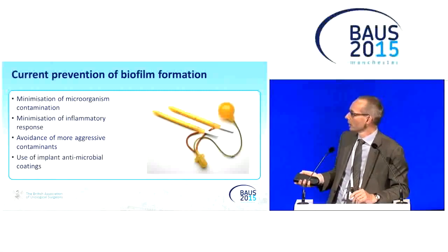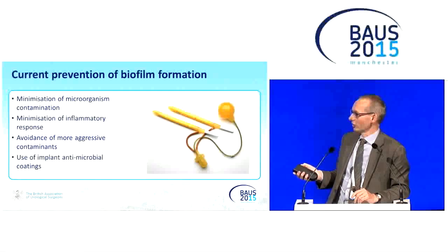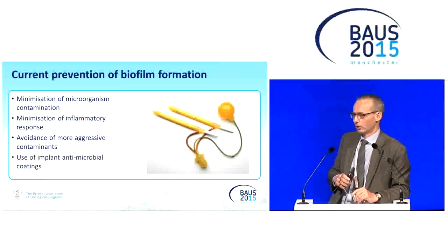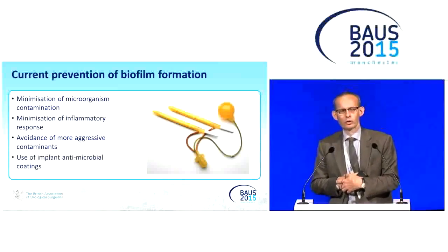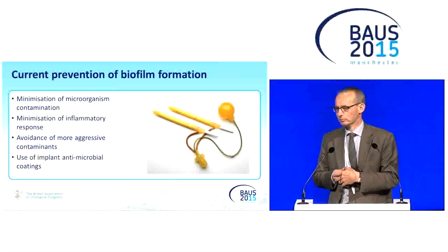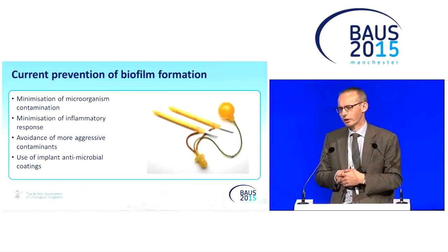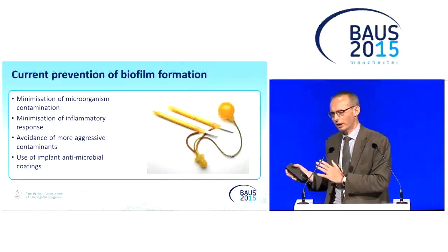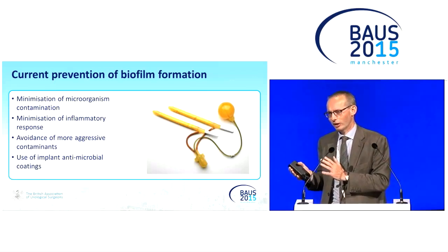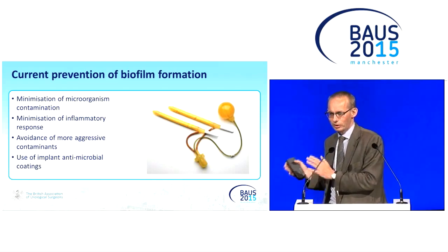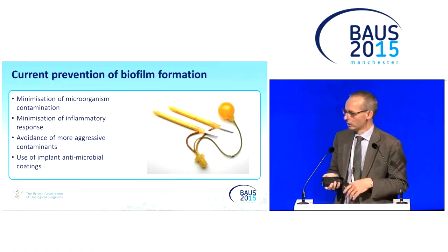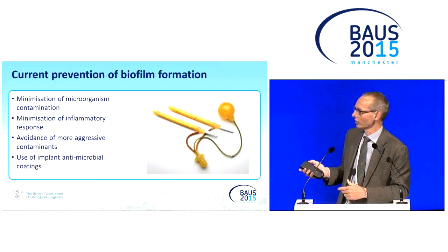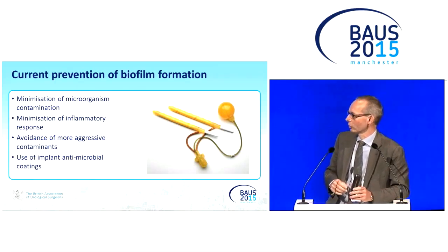And then one of the latest innovations on these implants, particularly the AMS ones, has been the coating of the implants with a mixture of rifampicin and minocycline. According to the reports from AMS, and a lot of this does come from Steve Wilson's work, that tends to minimize the slow chronic sinus infection type formation that eventually leads to removal. So it tends to reduce that, but it doesn't seem to reduce the more aggressive infections that mean instant removal. So it has changed things for the better, and it probably has reduced the risk of removal of the implant due to infection.